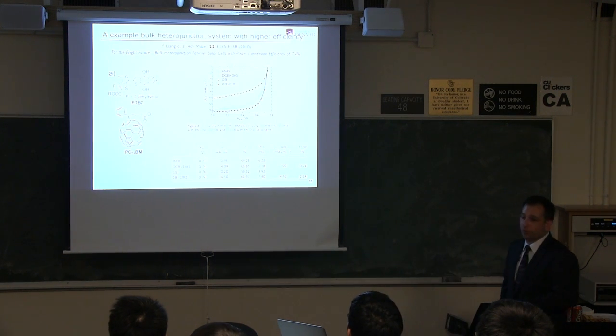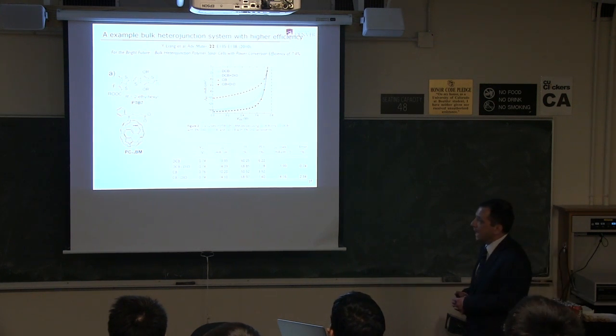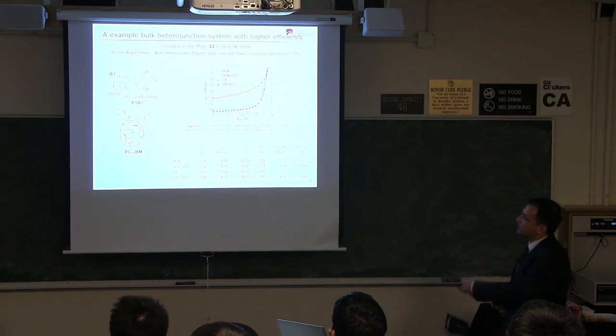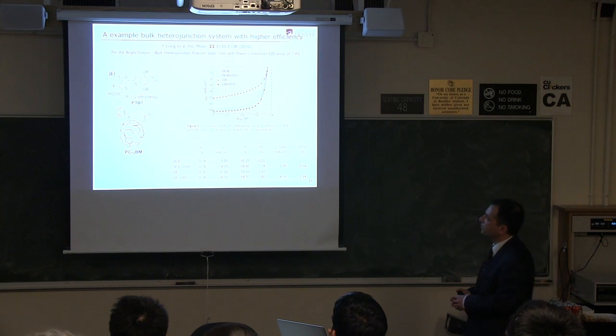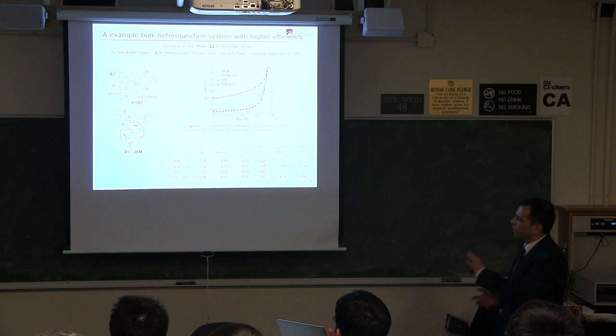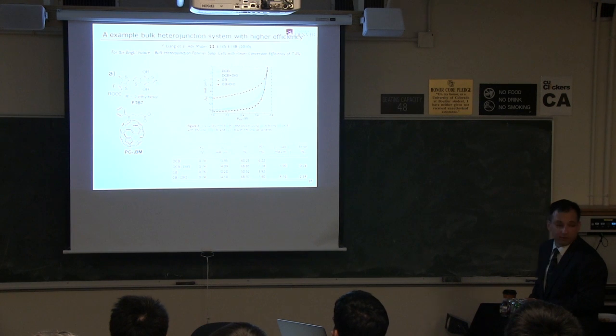If you want to do a lot better, you would need to use a polymer that has a more appropriate band gap. So P3HT's optical band gap is 1.9 electron volts, not very well matched with the solar spectrum. So this guy is a lot better. This is the material PTB7. I'm going to talk about this quite a bit. And band gap here is about 1.5 electron volts, or 1.6. And this gets you about 7% efficiency. And in the NREL lab, I think we're about there with PTB7. We've done that. Sarah's done that.